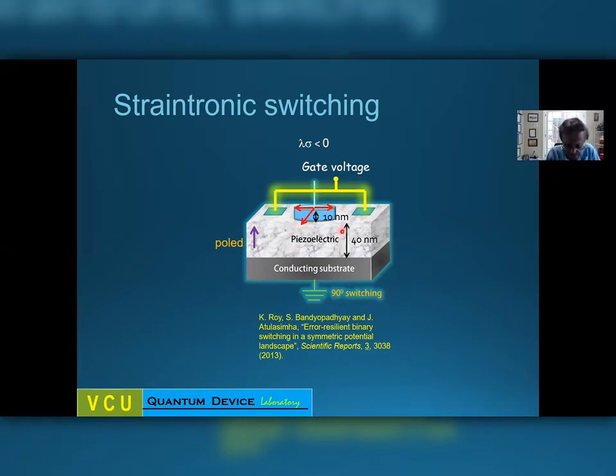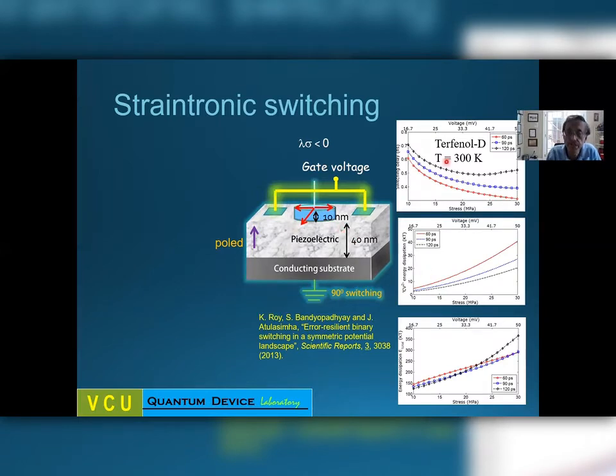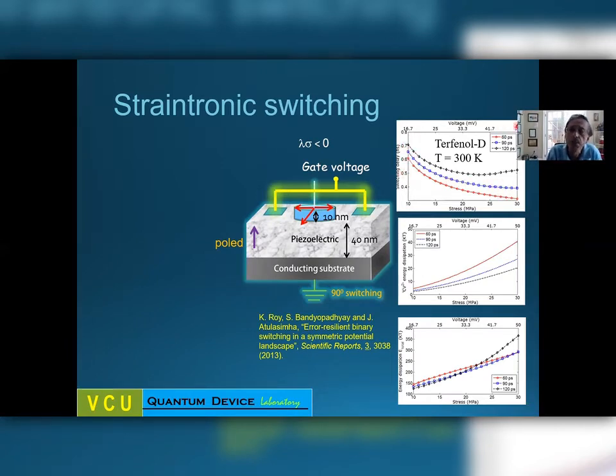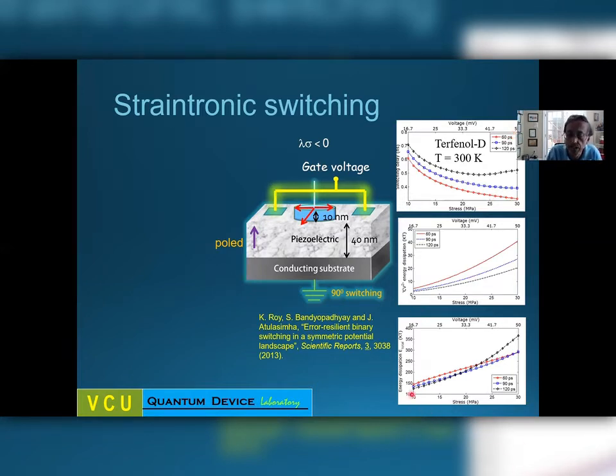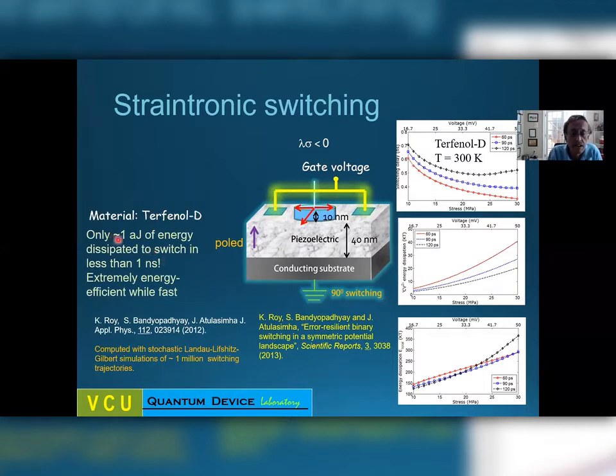The advantage of this is that you can switch fairly fast — in less than one nanosecond, with switching delays from about 0.7 to 0.3 nanoseconds. The amount of voltage you need to switch in that duration is tens of millivolts, as plotted here. So the energy dissipation is extremely small, and if you actually plot the total energy dissipation, you can see it's a few hundred kT at room temperature — slightly less than one attojoule if you use a material with high magnetostriction like Terfenol-D.